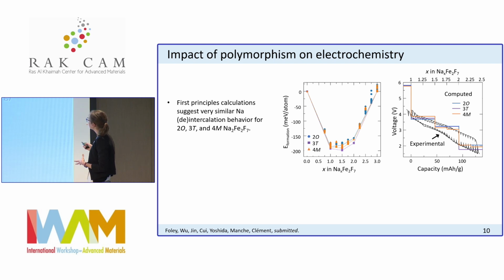But overall, the theoretical data agrees fairly well with the experimental data, but more importantly, what we are seeing here is that the 3 polymorphs are behaving similarly from a thermodynamic standpoint. So we're not really accounting for kinetics here, but thermodynamically, we would expect a fairly similar behavior for all 3 polymorphs, suggesting that polymorphism in this sample may not impact the electrochemistry as much as we think.